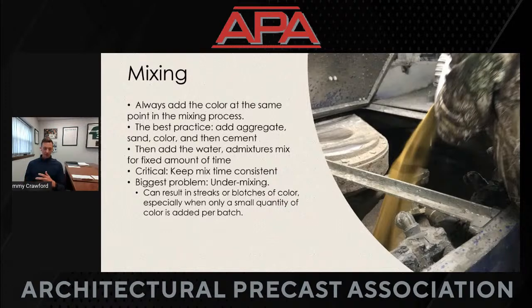Best practice, add your aggregate, add your sand, your color, and then cement. If you add in that order, you're going to get a good mix of your aggregate and cement and color before the sand hits it. That'll give you good color dispersion. Critical to keep your mix time consistent. And as I mentioned prior, the biggest problem that we see is undermixing. Undermixing can result in streaks or blotches of color, especially when you only use a small quantity of color in the batch.